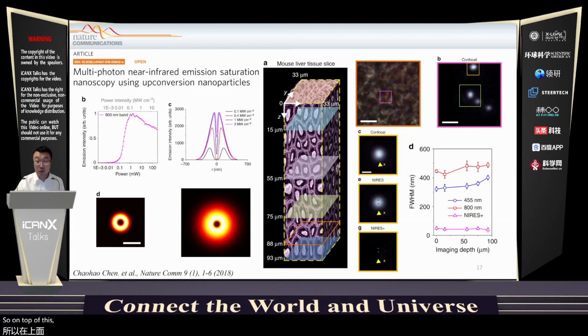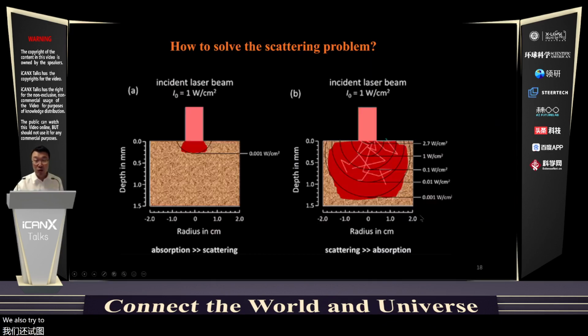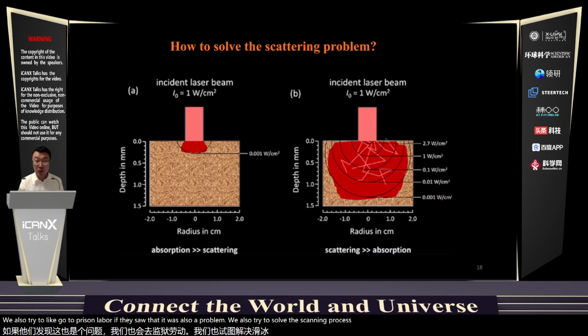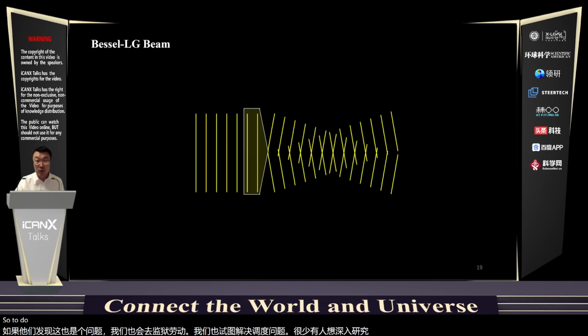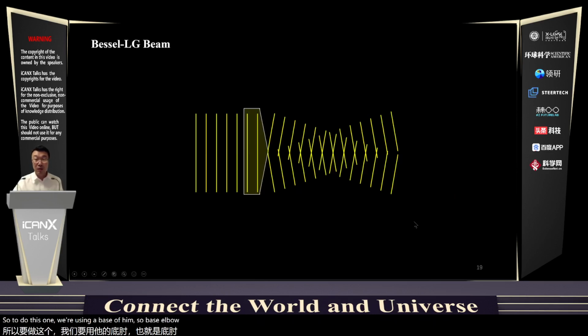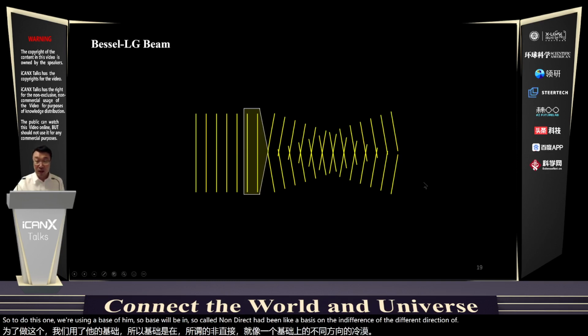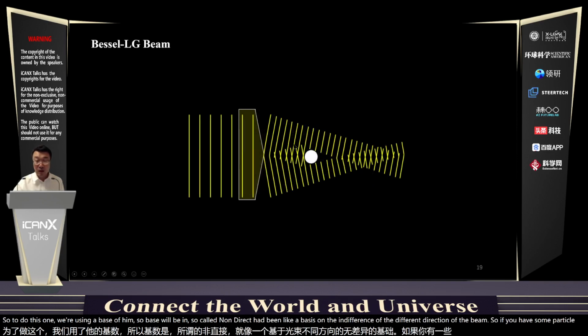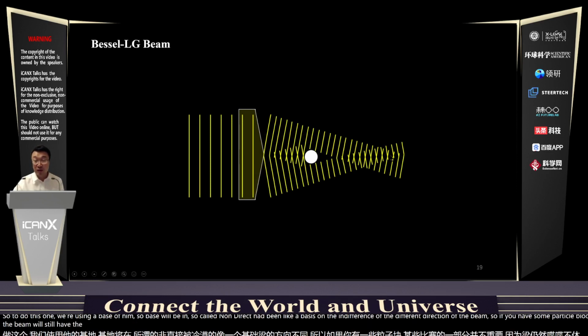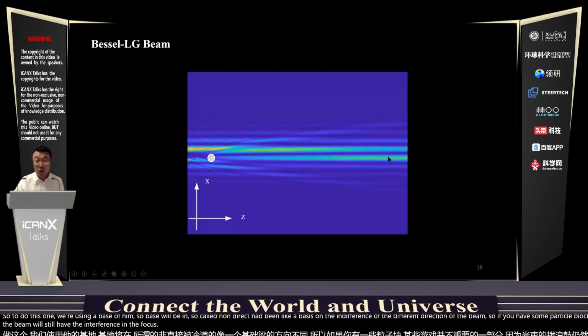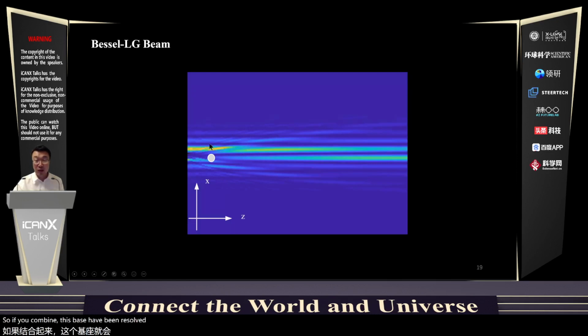On top of this work, because previously we solved the absorption problem, we also try to solve the scattering problem if you want to go even deeper. To do this, we use a Bessel beam. A Bessel beam is a so-called non-diffracting beam, based on the interference of beams from different directions. If a particle blocks part of the beam, it doesn't really matter, because the rest of the beam will still interfere at the focus. If we combine this Bessel beam with our donut beam, we have the Bessel donut beam. So you will see that if we put a scatterer somewhere, we still have a nice focus.